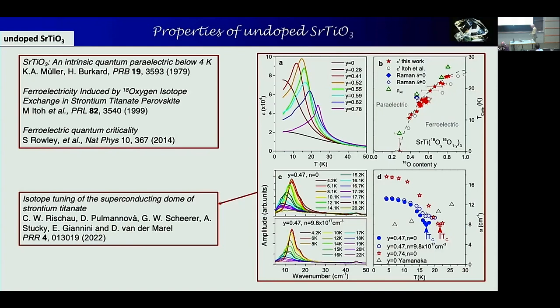One direction that was actually initiated by Müller was using a calcium substitution on the strontium side, or as was found out later by Ito in 1999, you can do oxygen 18 substitution on the oxygen 16 positions, and because the oxygen 18 is heavier than oxygen 16, you suppress the quantum fluctuations a bit, but just enough actually to push it across the boundary of becoming a ferroelectric substance at low temperatures. There are ferroelectric transition temperatures, Curie temperatures, that depend on the doping, but it can get as high as 30 or 40 Kelvin. I'll show you, actually there are examples here.